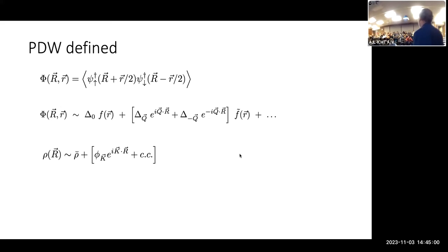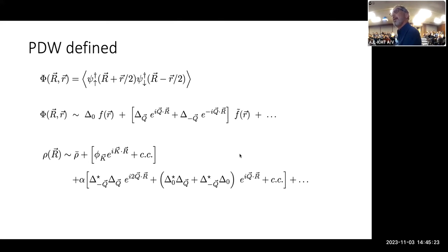I'm also going to be talking about diffraction experiments. So the charge density is going to be an important player in the discussion. And the charge density is some uniform piece. Then if there's a charge density wave, that's described by a single complex order parameter and a wave vector K. But if we had these modulated superconducting orders, then we're going to also get induced density wave order from a gauge invariant combination. So this is delta star delta, this is gauge invariant, but it oscillates at period 2q. Or as a cross term between uniform and pair density wave order, we're going to get something that oscillates at 1q.